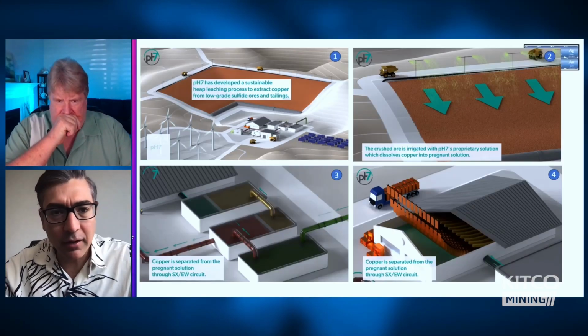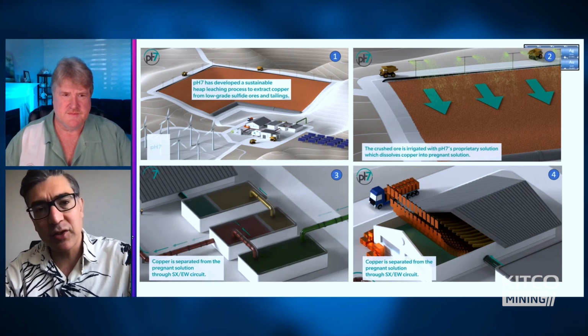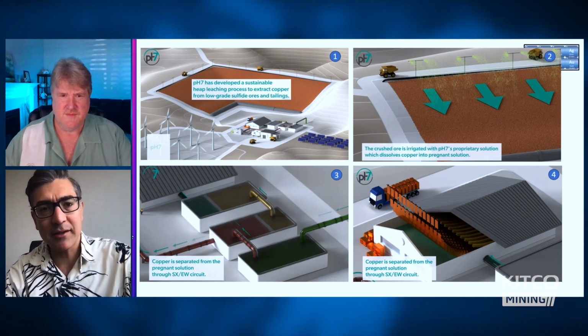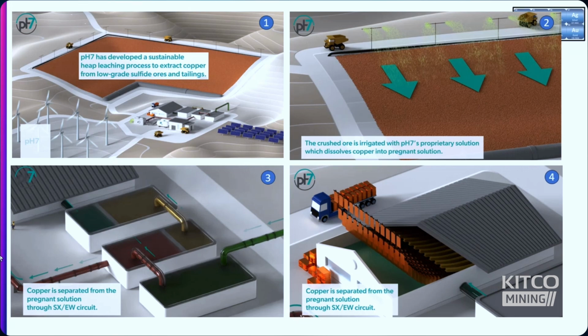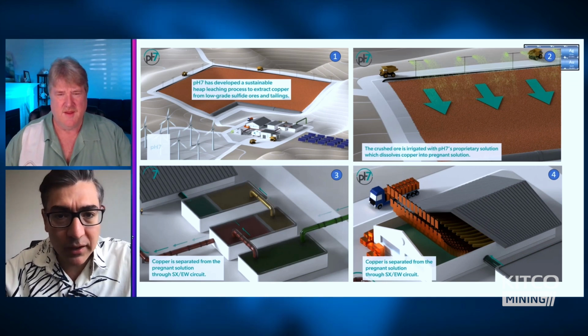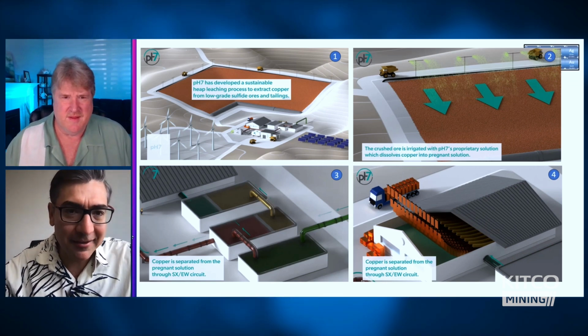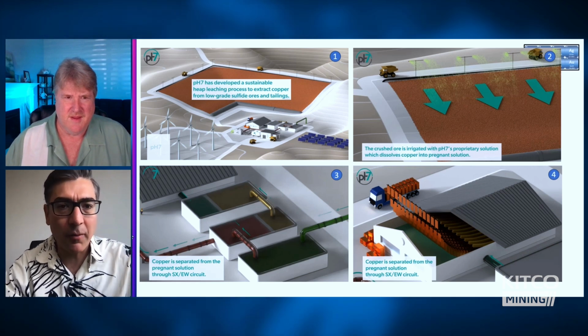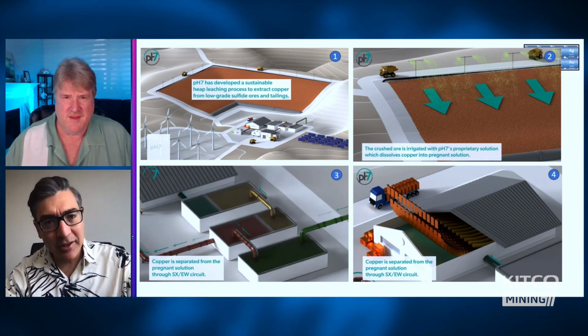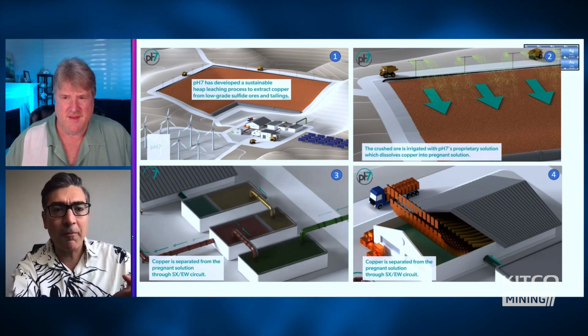And then there is no wastewater, there are no tailing ponds. The reclamation of the site is very easy compared to sulfide ore. So what we are targeting to do at PH7 is enabling that heap leaching process for sulfide ore, and enabling it for the entire mining operation. And how we do it is, again, through our electrochemical process and organic ligands that we developed, that can oxidize the copper and leach it into the solution. So we can break down the sulfide copper bond and oxidize the copper through those electrochemical reactions, and then bond it with our organic ligands to dissolve it into the solution.